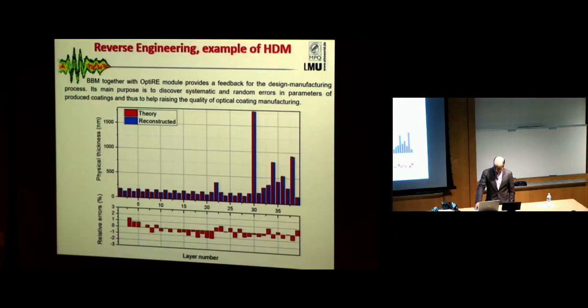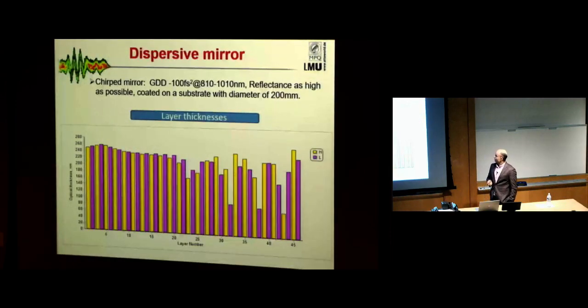for this particular mirror. Actually, when we go to produce a real structure, I want to give you an example for dispersive mirrors which provide minus 100 femtosecond squared delay in the range from 810 to 1010 nanometers. It has a bandwidth of 200 nanometers. The layer structure looks like this. We have high and low refractive index material here. We have different frequencies. In this particular structure, luckily, we don't have very thin layers. The thinnest is just 80 nanometers. The thickest is about 260 nanometers.